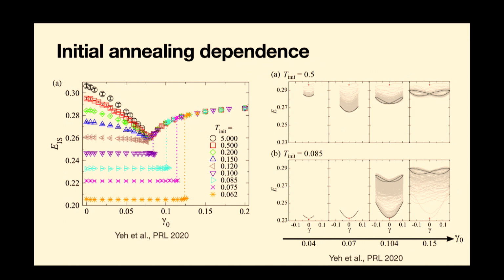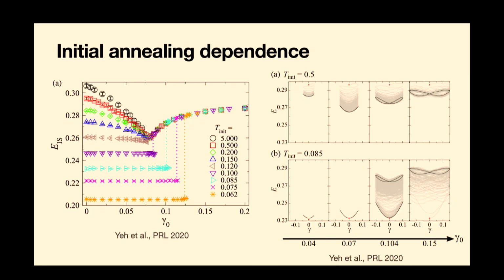So what's interesting now is when you combine this aspect, you have this dynamical transition, with the fact that these systems are already out of equilibrium, so how they behave depends on how you've made them, right? They're not equilibrium structures. So there is, in this response that I've just described, a further dependence on how non-equilibrium the system is when you start. Okay? And that's in the glass literature typically called the initial annealing dependence, basically how well have you prepared the sample in terms of how low is its energy when you start. If it's low in energy, then you say it's well annealed, as you would do with the glass if you cool it slowly. If it's high, then you say it's poorly annealed.